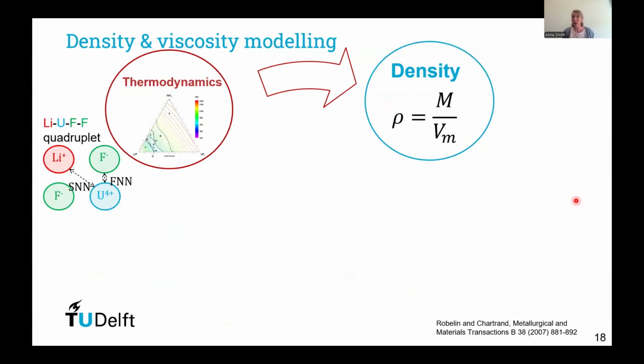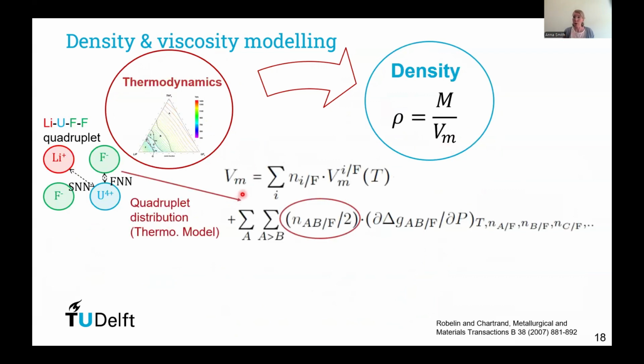The density is related to the molar mass and the molar volume. And this molar volume can be expressed as follows. And this is an expression that was developed in the previous work of Robelin and Chartrand already some years ago. And so we have used the same approach and applied it to our nuclear fuels. So this molar volume is expressed as a stoichiometric sum of the molar volume of the end members plus an excess contribution, which represents the deviation from ideality of this molar volume.